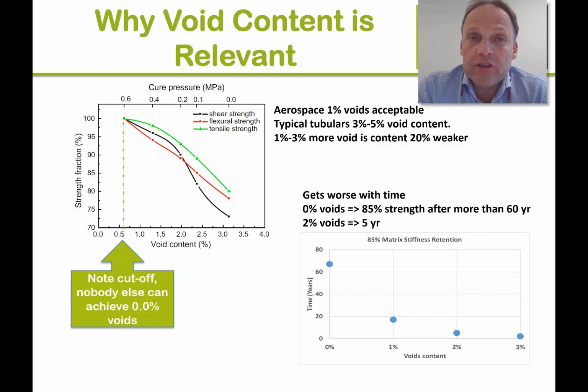Another aspect of composites is void content, because ideally a composite is made of resin and fibers, and there are no voids in the composite structure. Now why is that so relevant to voids? In the graph on the left hand side here, you see that with increasing void content on the bottom axis, the strength fraction decreases. So with higher voids, you have to compensate for the strength of the material by degrading it. And very typically at 1 to 3% more void content, the composite structure will be up to 20% weaker.